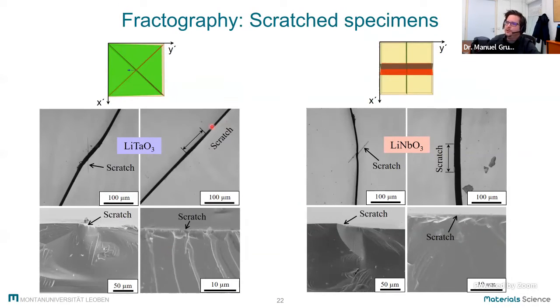So we can see for scratches parallel to the cleavage plane that at this origin of fracture, the cracks go through the material without any disturbance of the cracks. And if we do the scratches in a certain angle to the cleavage plane, again, the origin of fracture is the scratch, but then the crack has to turn into a plane with lower fracture energy. And also, as we saw before, the impact of the scratch is not so severe for such a direction. And this can explain the difference in strength for the materials.